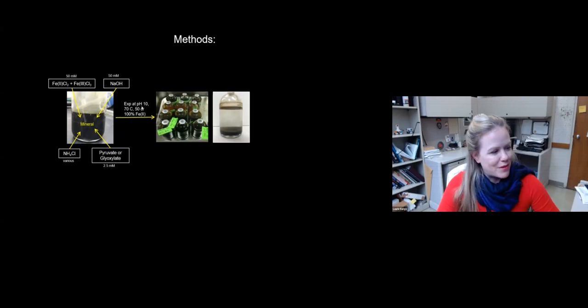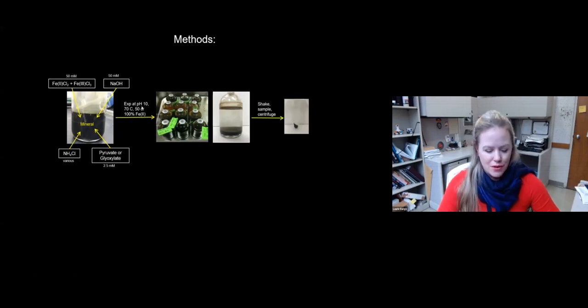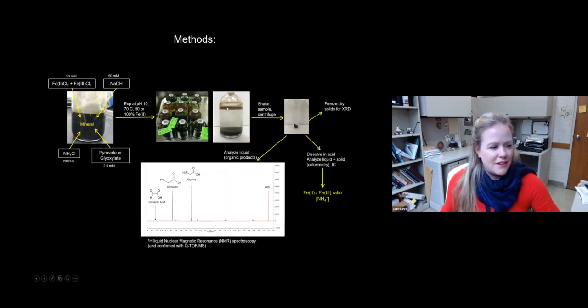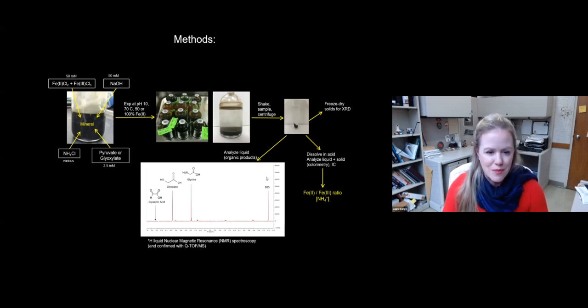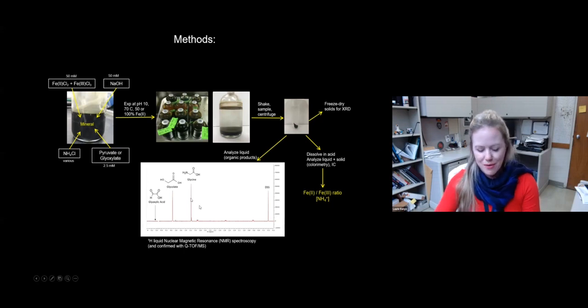So they react in an anaerobic chamber, and then at the sampling time, we take a sample, we centrifuge it to separate the solid and liquid, and then the solids get freeze-dried for X-ray diffraction. They can be dissolved in acid to become a liquid again, and we can analyze the iron 2 to iron 3 ratio in the solid. And then the liquid products get analyzed with organic analysis, in this case, proton NMR. So that's nuclear magnetic resonance spectroscopy. And we just get peaks for each organic that's there, and then we can quantify their abundance.